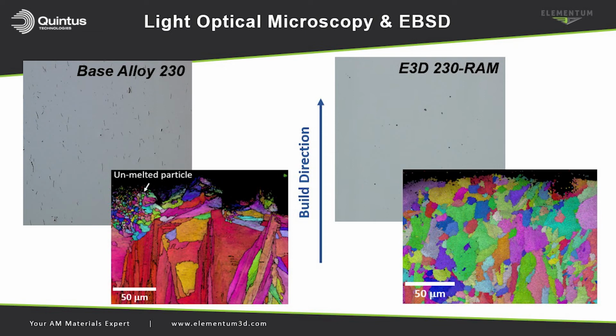So we found that with the RAM process, we can eliminate that microcracking and get a huge performance gain on its own. Now, in the AM process, there's going to be inherent defects that are going to be present. There's always going to be some level of porosity, even if it's relatively minimal compared to other casting and so on approaches.